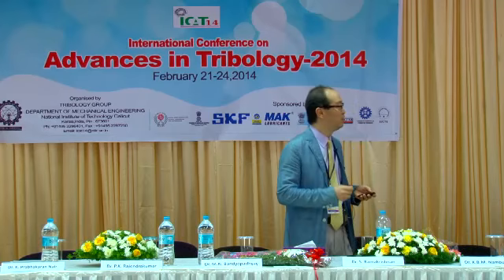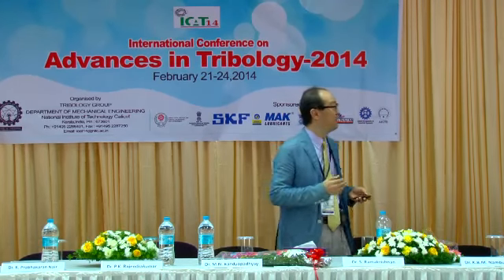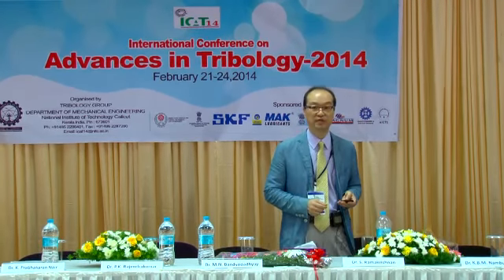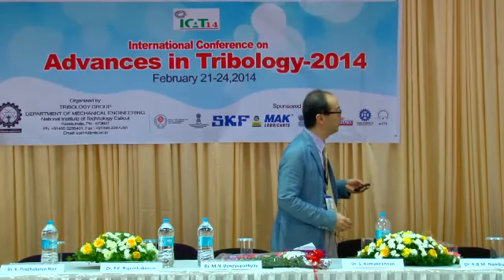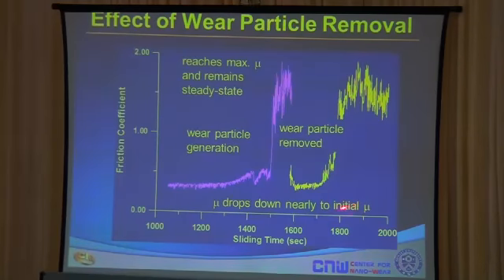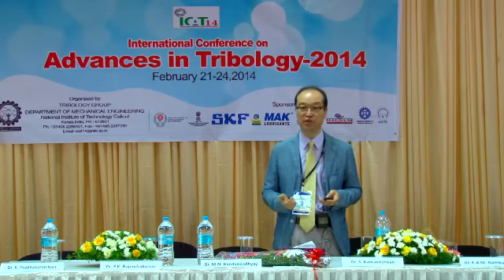By knowing this, we can reduce friction if we eliminate the wear particles. And indeed, this data shows that. This is the friction coefficient versus sliding distance or time. As you can see, the friction coefficient begins to increase again, and when the particles are removed, it goes down. And the particles are created again, and the friction coefficient goes up again. Now, in this case, the particles were removed artificially using a brush. Now, how can we do this automatically?